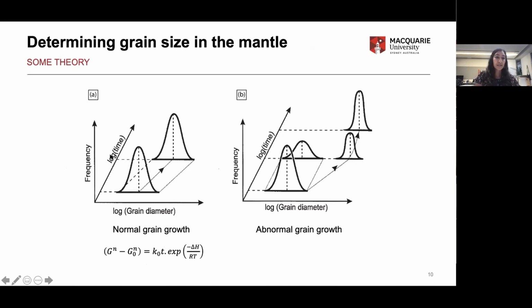This tells us the rate at which our grain should be growing in a given pressure and temperature space, and it will also define the long-term trend and mechanism for grain growth. For cases where we have abnormal grain growth, we lose that log normal distribution with time, and the shape of that distribution will change. So this is just truth checking what we find in our experiments and ensuring that we're able to actually measure normal grain growth.